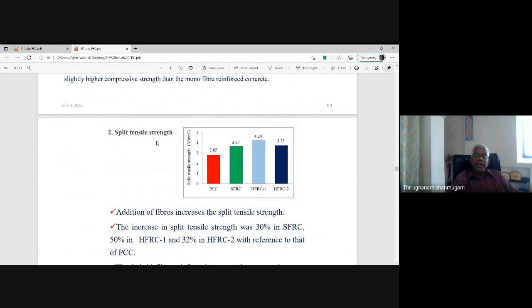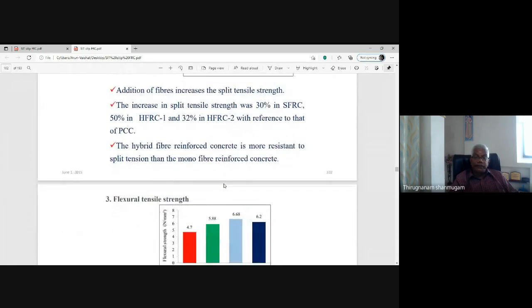Similarly, the split tensile strength 2.8 Newton per mm square, 3.67 Newton per mm square, and 4.34, 3.73. This split tensile strength is improved very much, such as 30% or 40%, because of the inclusion of fibers. The fibers are acting as the crack arrestor. 30% increase in SFRC, 50% increase in HFRC.